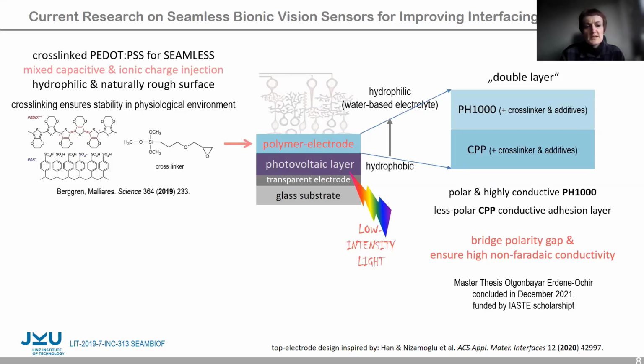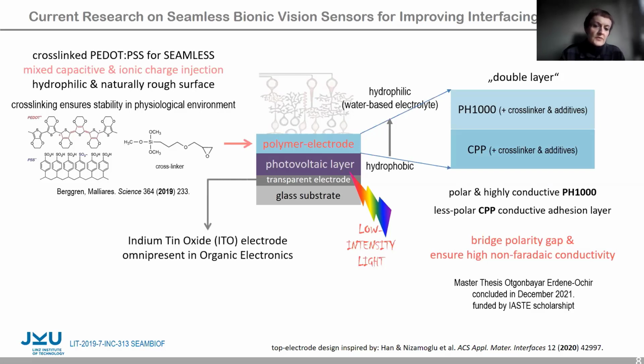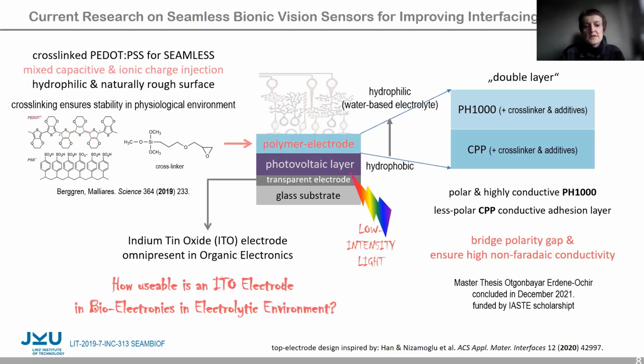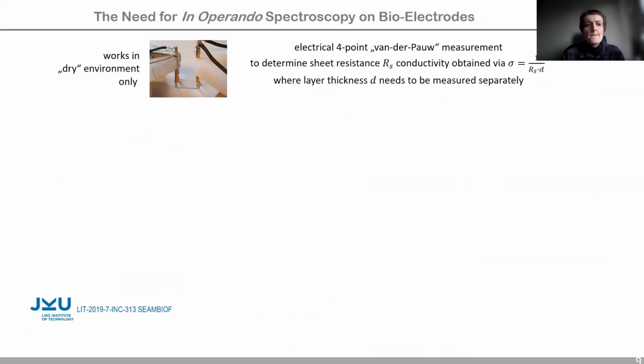The PH1000 is highly conductive due to its capability to swell in water and to soak and release dissolved ions. But let's have a look at the bottom of the device. There's an electrode as well to support the photovoltaic effect. For convenience, we use the commercial indium tin oxide or ITO electrode, which is omnipresent in organic electronics. But how useful is such an ITO electrode in the wet electrolytic environment of a bioelectronic device?